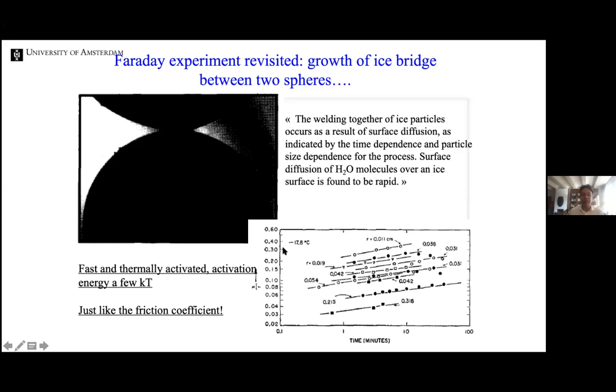The question about the activation energy: we know what the activation energy for surface diffusion should be, and we actually find something very similar to the one found by Kingery for this sphere sintering experiment. So it's just a few kT. We're trying to do better in the self-healing ice experiment, where we can quantify things much better than either Kingery or our skating experiment. Okay, thank you.